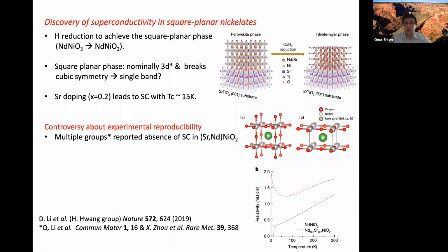And before I go any further to provide my theoretical understanding of this compound, I would like to address an issue that came up many times when I tried to write papers or proposals on this compound: there are multiple reports on experimental reproducibility. People tried to do the same thing, at least these 2 papers, and didn't find any superconductivity. And of course, this is a problem because science is only science if you can reproduce things, right? But it turns out growing these films is extremely challenging. It took like 5 years for Harold Hwang to actually do this experiment, and to expect completely different groups to grow these in a few months, it's not clear if their samples are clean enough.